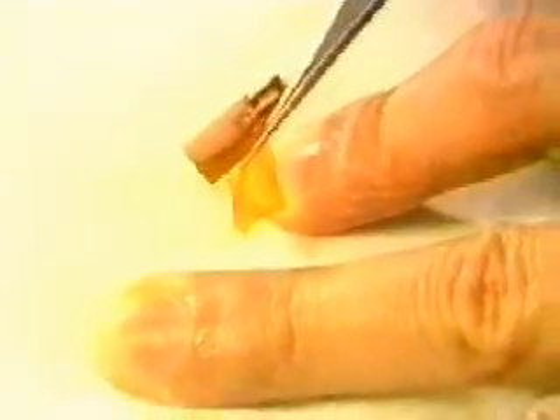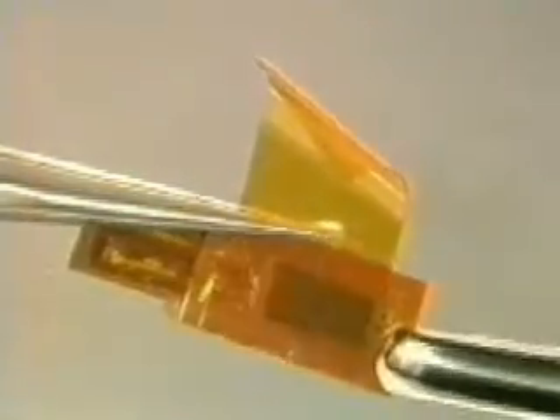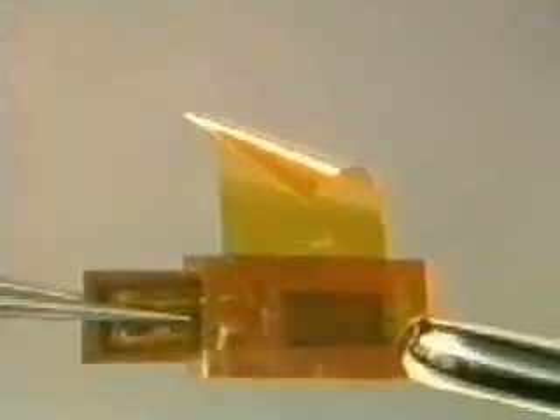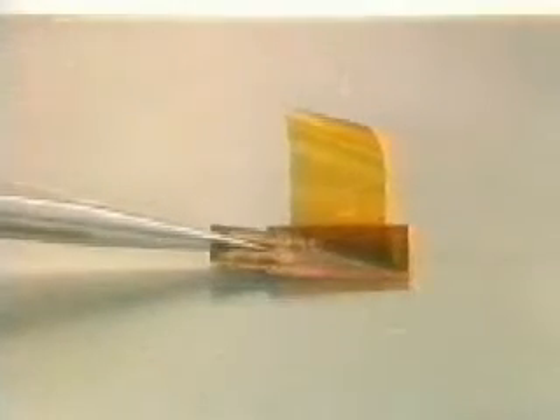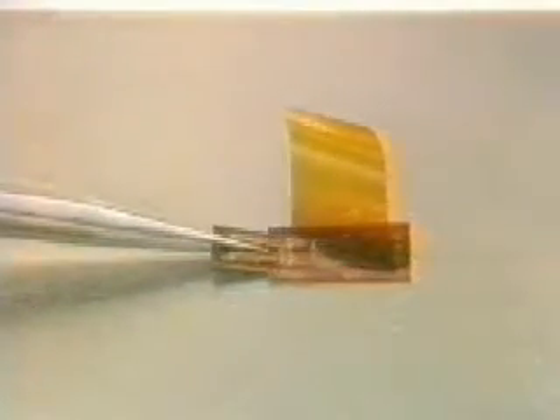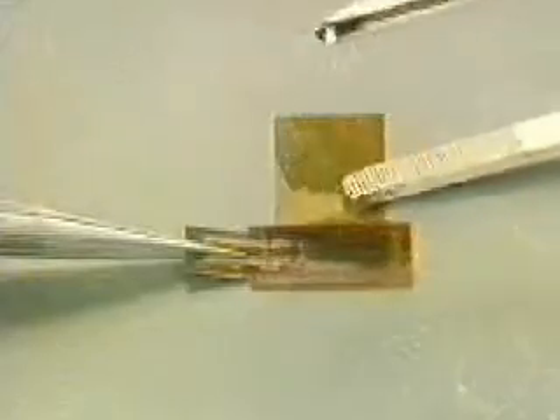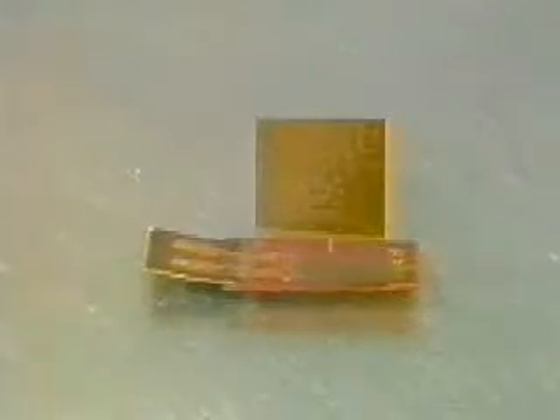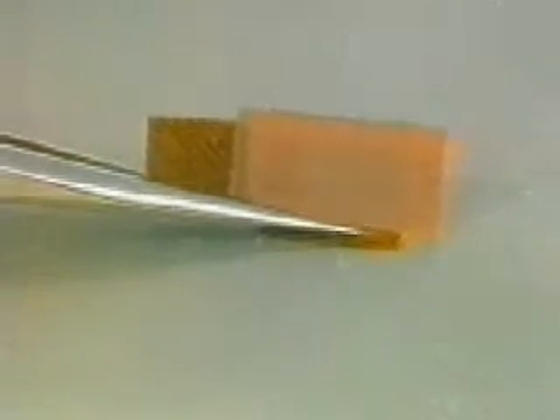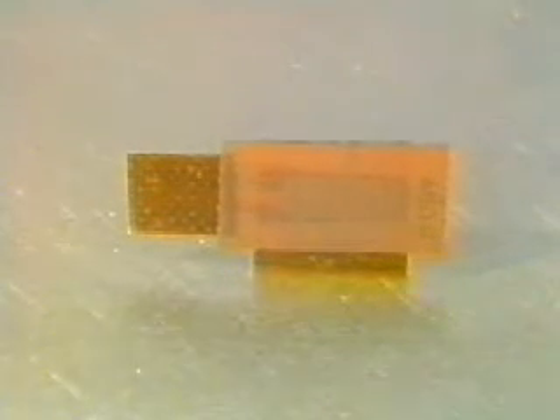The strain gauge is now transferred to the test object. It's held by the tweezers between the two solder terminals so that the markings can be easily seen. Then the axis markings on the strain gauge are lined up with the cross on the test object. The strain gauge is fixed in the correct position with the adhesive strip. The adhesive strip should now be pulled back about 1 to 2 millimeters with the strain gauge, and the strain gauge is folded back so that the strain gauge adhesive can also be applied over the edge of the strain gauge on this side.